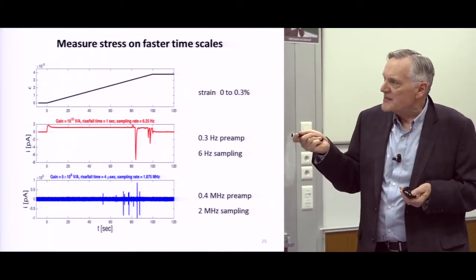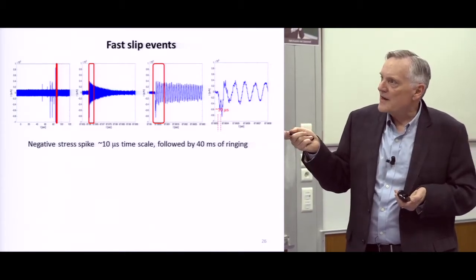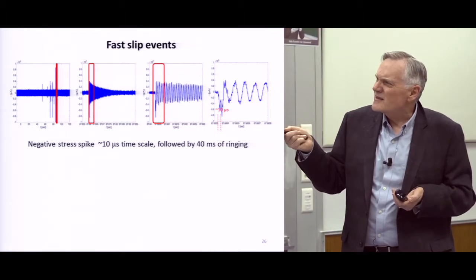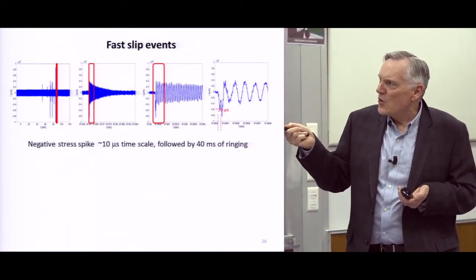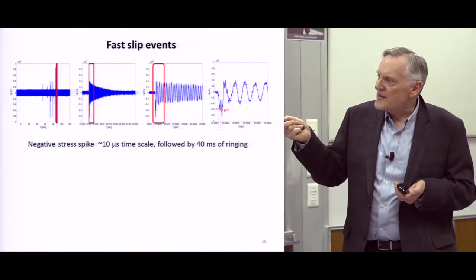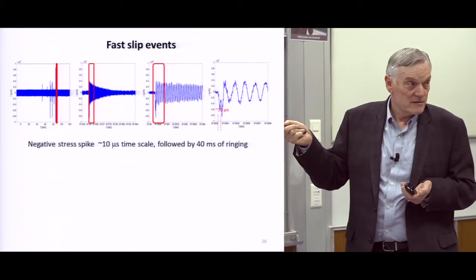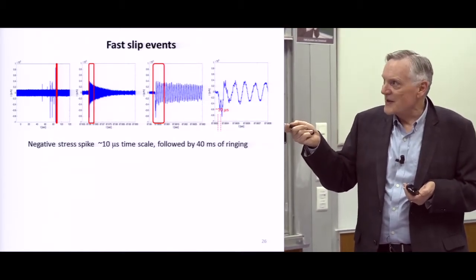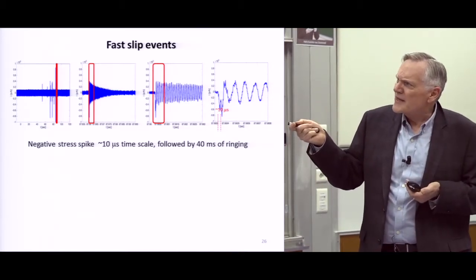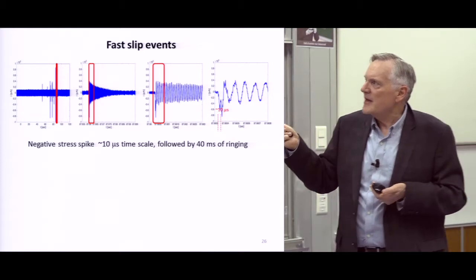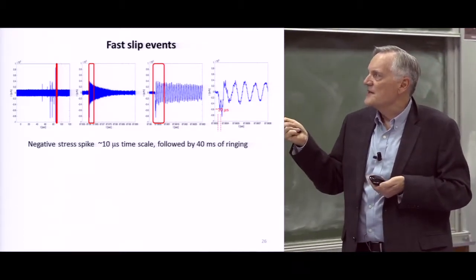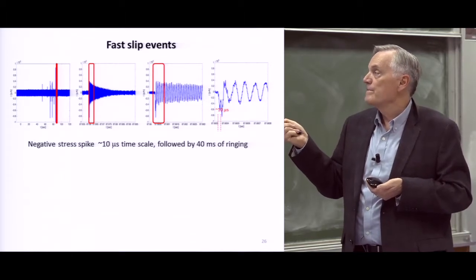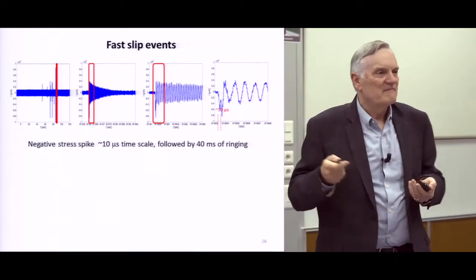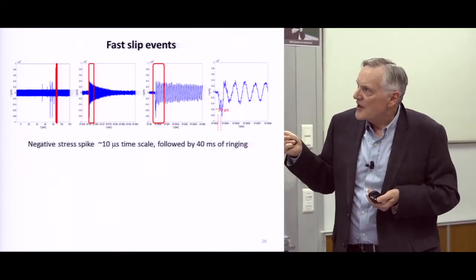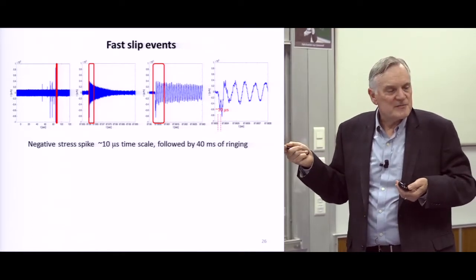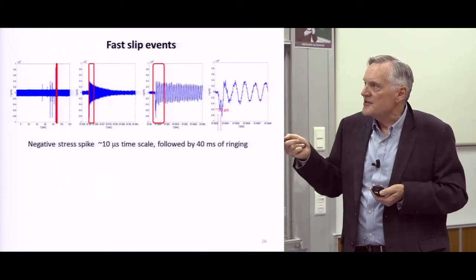Okay, so we did that. If we take this biggest spike here and blow it up, this is 100 seconds, 120 seconds. This whole decay is, I don't know, 5 milliseconds. Something happens, and it's not a spike. There's something decaying over about 40 milliseconds afterwards. But if I blow a few milliseconds up and blow it up again, by the time I get to here, this whole time length is, I don't know, 50 microseconds or something like that. There's a sudden drop, which means a little bit of stress has been relaxed, there's been a little bit of slip, and it's followed by a bunch of oscillations that go on and die out slowly.